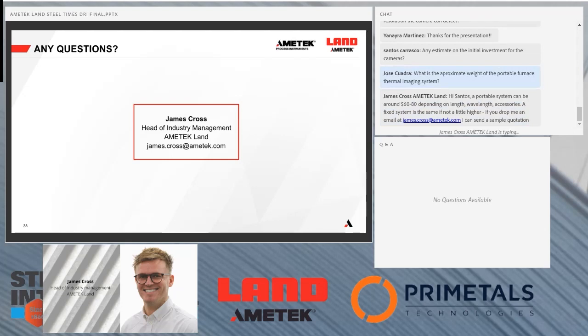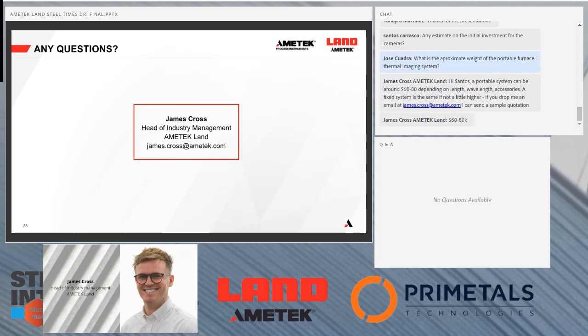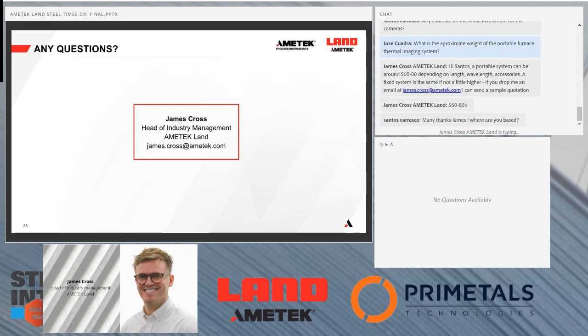We still typically like this pellet size in the range of 9 to 16 millimeter. But with that gangue, you sometimes can create more fines. So there's a little bit of productivity concerns. But like we said, there's a few commercial DRI plants running blast furnace grade pellets now and not having real issues. So we don't expect it to change much. And their pellets are a little more abrasive as well, the blast furnace grade. So a little more wear and tear, but process wise, the reduction would basically still be the same. Okay, thank you very much.